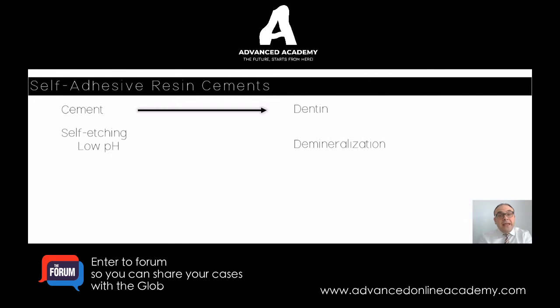We need that pH to be low so that it can partially demineralize the dentin and the tooth structure. So this low pH is going to demineralize the dentin and enhance the bond to the tooth structure. For the self-adhesive to penetrate deep into the dentinal tubules, it has to be hydrophilic, and that will increase the wettability on the dentin surface.